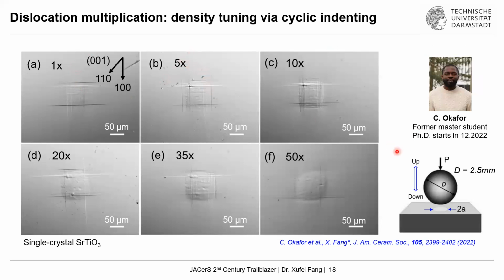So the next step, we were thinking about what happens if we use a much, much larger ball indenter, in this case, 2.5 millimeter. And the interesting thing that happens, again, is it does not show cracking anymore, but rather, again, pure plastic deformation. We also started doing the so-called cyclic indentation, meaning that 1x means one time indent, 5x means 5 times indenting in the same location. So we basically loaded, unloaded, and loaded and unloaded 5 times, even up to 50 times.